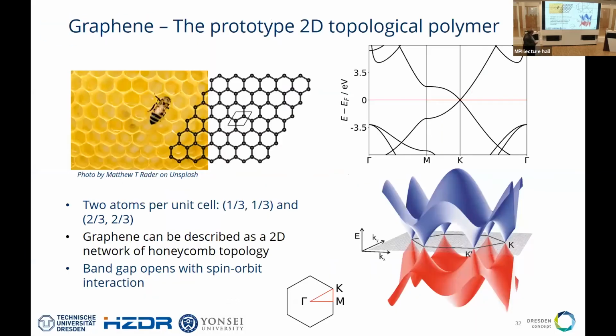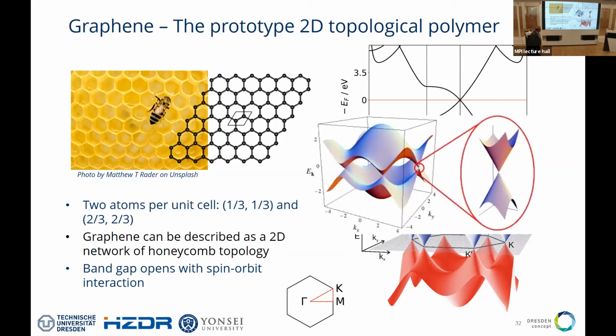And I would like to show you that we can if we do a little bit of chemistry. So we all know graphene, very, very simple slide. Why do we have a Dirac cone in graphene? The reason for that is we have a honeycomb lattice. It's not because of carbon, but it's because carbon makes a honeycomb lattice, and that we have 1 electron left, so per carbon atom, that is actually making this pi system. That pi system forms this very beautiful Dirac structure. And if we include spin-orbit coupling, then we actually see the band gap opening, we can see the topological state, etc. So that is very easily understood with graphene.